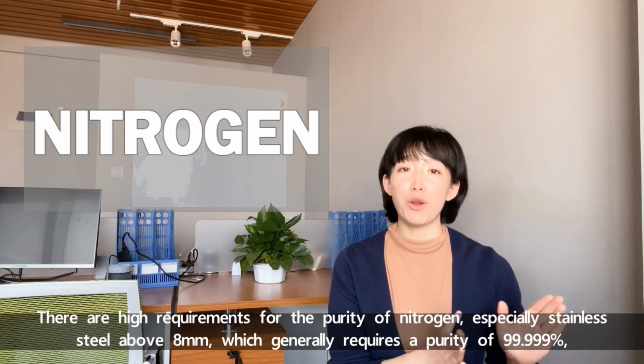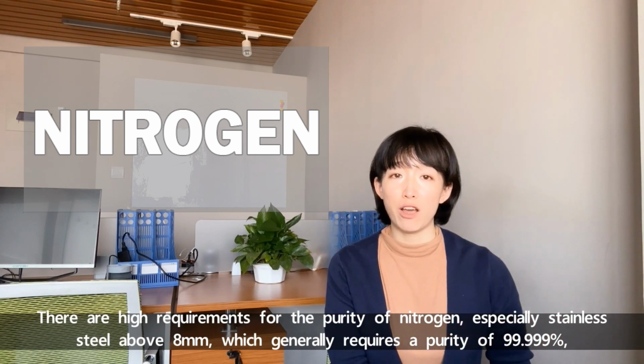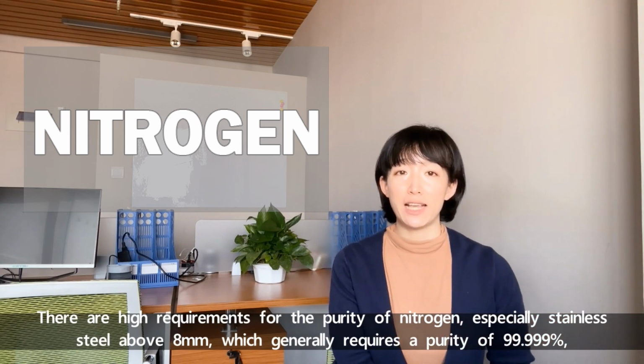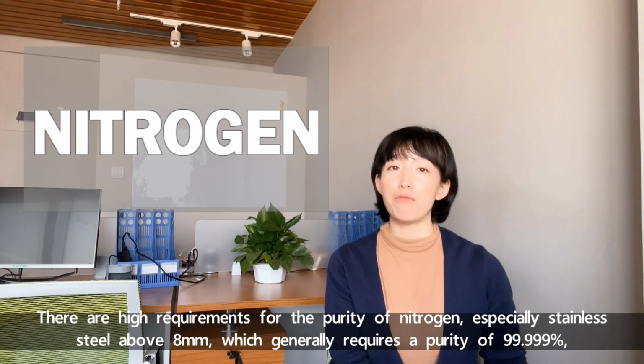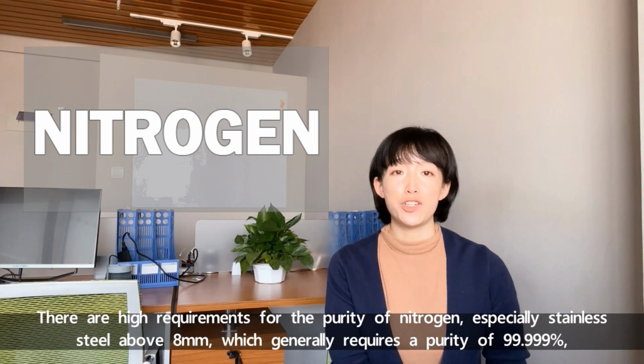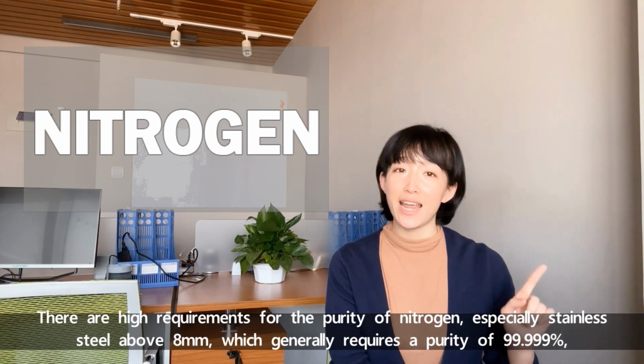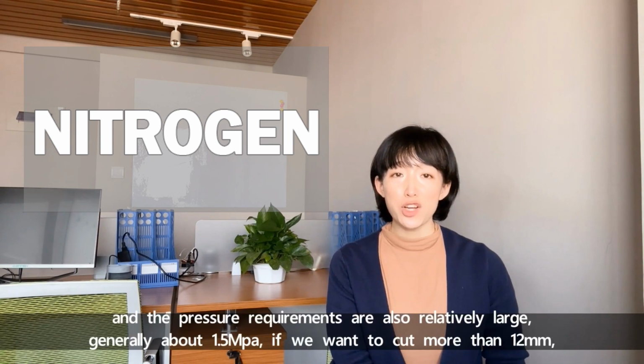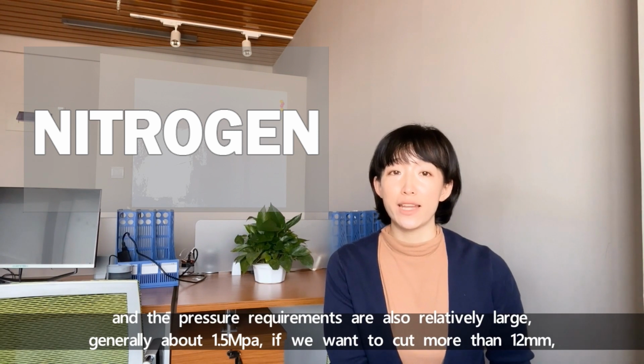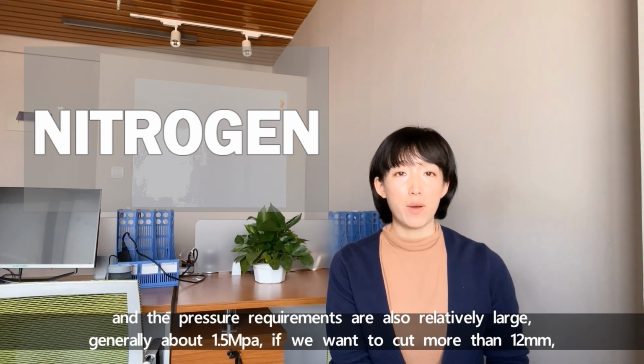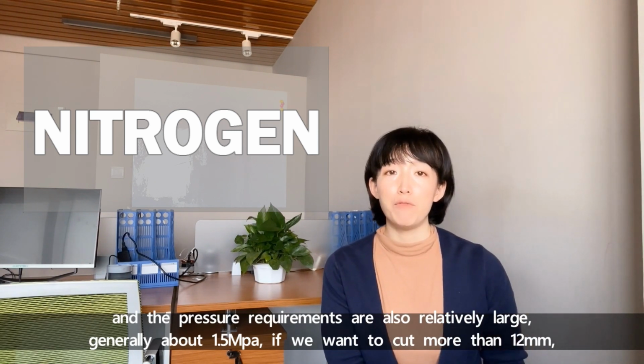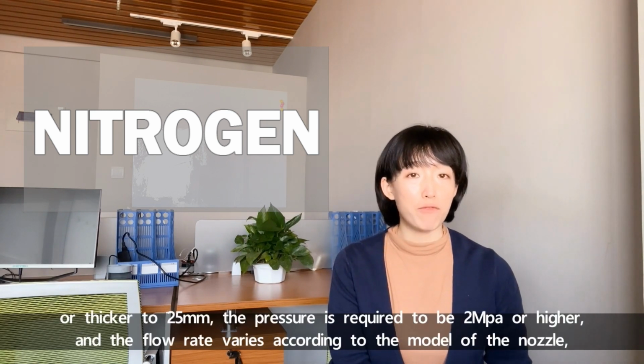There are high requirements for the purity of nitrogen, especially when cutting stainless steel above 8 mm, which generally requires a purity of 99.999%. And the pressure requirements are also relatively large, generally about 1.5 MPa if we want to cut more than 12 mm, or thicker to 25 mm, the pressure is required to be 2 MPa or higher.